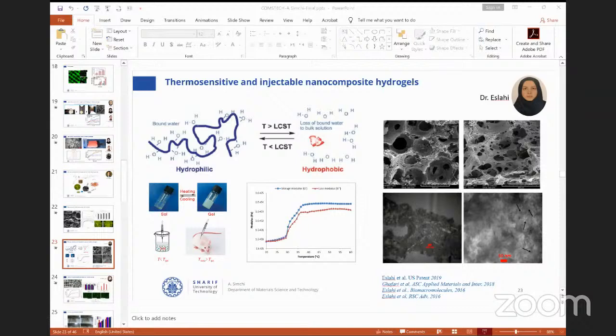One of my postdocs, Dr. Eslahi, was successful to show that, as you see in the graph, please note that it shows the modulus of elasticity versus the temperature. So at low temperature, the material is fluidable. When it is injected in the body, around 37 degrees centigrade, the body temperature, it transforms to a gel. Therefore, it can be used for cartilage tissue engineering.